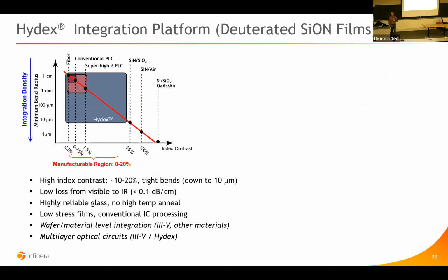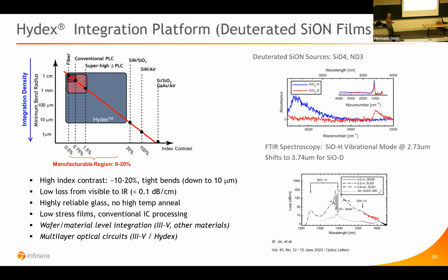Now I'll go into a little bit more depth about a platform, and we're in the process of bringing this platform up, called Hydex. Hydex is a platform that uses deuterated silicon oxynitride. What that does is, by using deuterated sources instead of conventional silane and ammonia, we can push the vibrational mode in the absorption for the silicon, oxygen, hydrogen that's normally at 2.73 microns all the way out to 3.74 microns when it's deuterated. And because we push that out, we then lower the absorption in the infrared, and we actually lower the absorption, I'll show you later, in the visible as well.